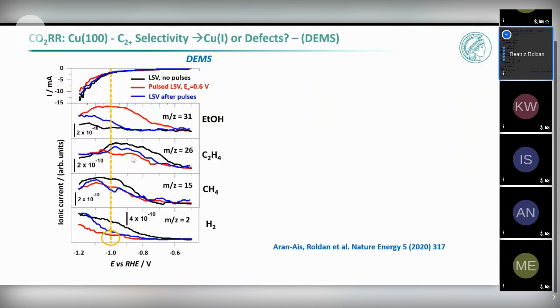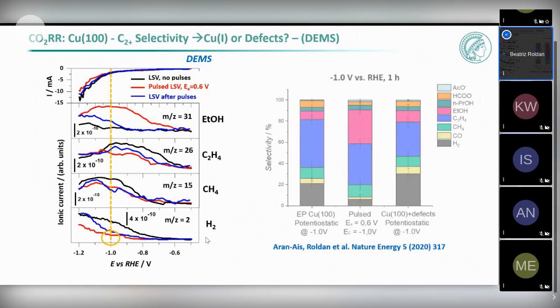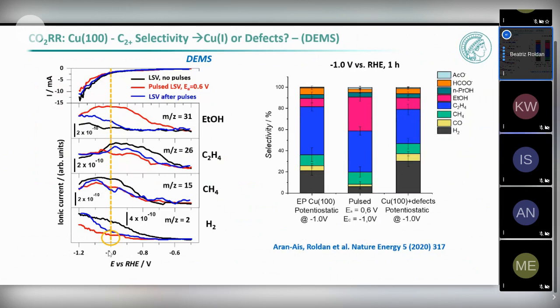We see also a correlation with the amount of ethylene. So we favor the production of ethanol, it seems, at the expense of ethylene. And in all of the pulse treatments, we minimize the production of hydrogen. You can see here, when we look at -1 volt, you can see here the selectivity data again. This is when we run the reaction under potentiostatic conditions at -1 volt. Here is when we apply the pulses, we see clearly the increase in the ethanol and the suppression of hydrogen.